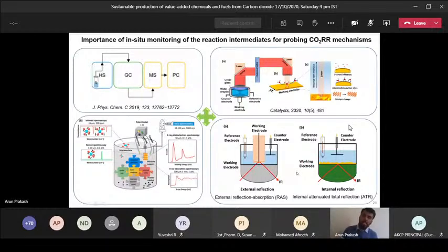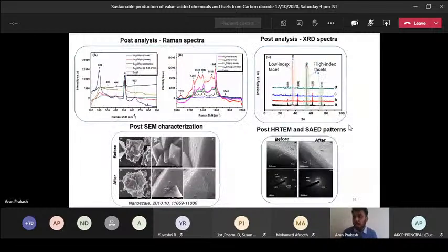After CO2 reduction, you still have to check your catalyst, whether it is still stable or not. How can you confirm the stability of your catalyst? Run your CO2 reduction for 1 hour or 2 hours or 3 hours. After your CO2 reduction, just collect your catalyst and go for some spectroscopic analysis.